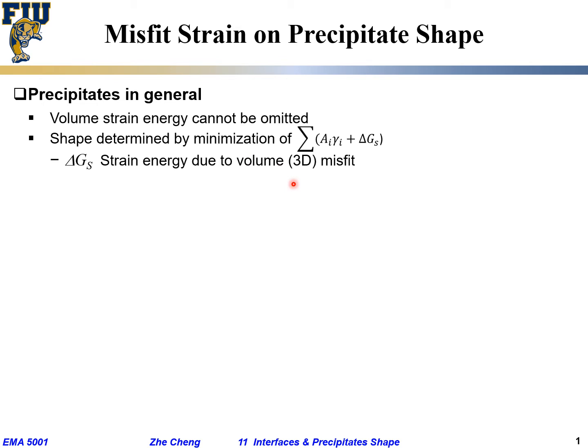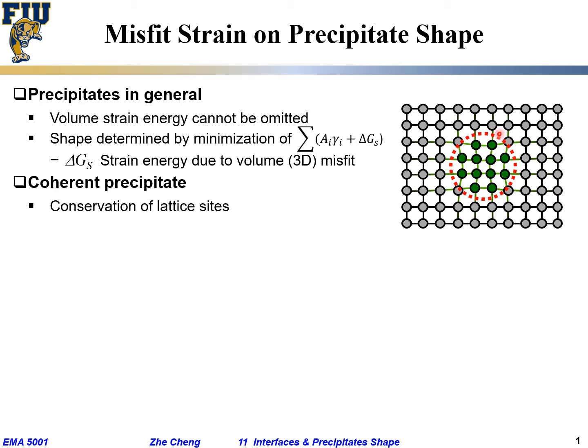The hole is smaller than the precipitate, which means when you put the precipitate in there, it's going to push everything around — other than the mismatch in 2D, in-plane. For those cases, if we have a so-called coherent precipitate, which means they try to match at the interface bond by bond, then we are going to have conservation of lattice site. The precipitate volume-wise would be either larger or smaller than the hole, but they still try to match — the bond will be tilted, they would try to squeeze or pull.